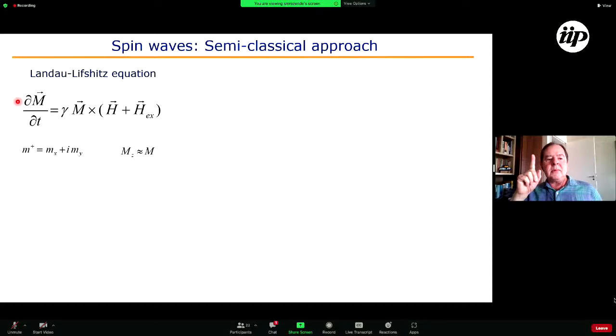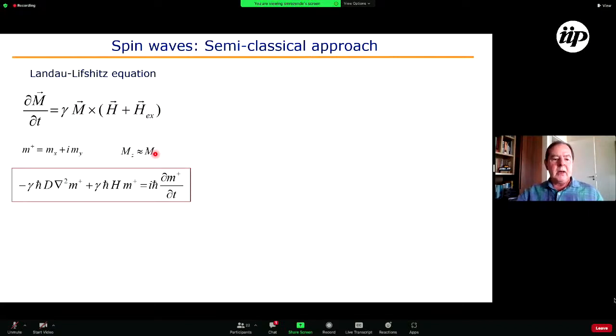We call the direction of the applied magnetic field, the equilibrium direction, the z direction. So we introduce a variable, mx plus i my, which denotes the transverse magnetization, and the z component of magnetization is approximately the magnetization itself. Well, if we use the equation for the two components and introduce this variable here, we get a very interesting equation.